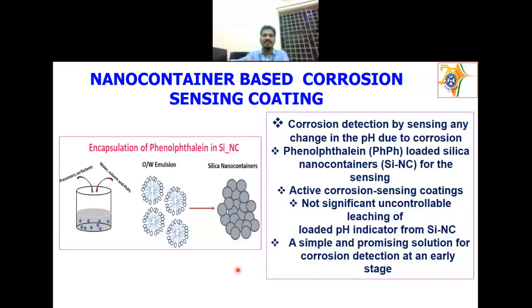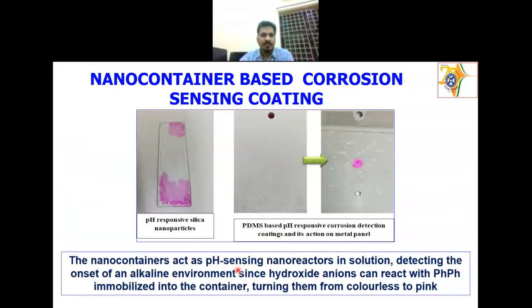So what we did is we made some silica nanocapsules, and we added an indicator here. Phenolphthalein, as we know, is the indicator which can sense when an alkaline environment comes, turning from colorless to pink. We loaded this inside the containers, and then these are the containers. We drop-casted them on a glass slide to check whether it is able to sense it or not.